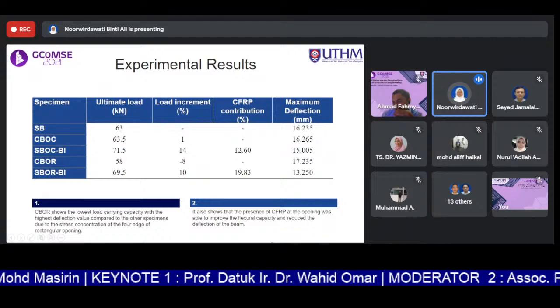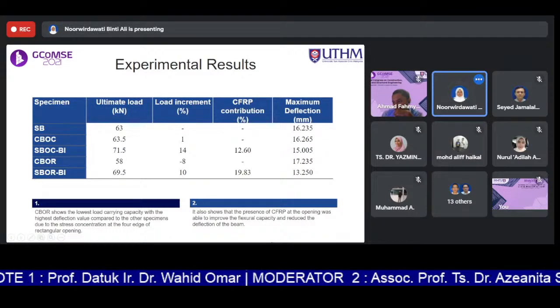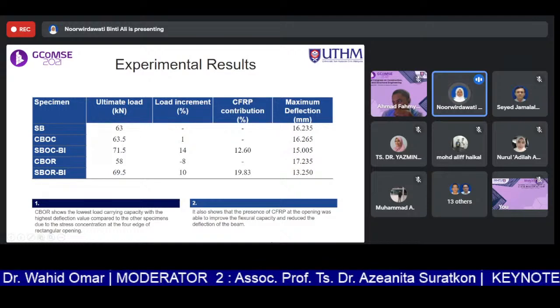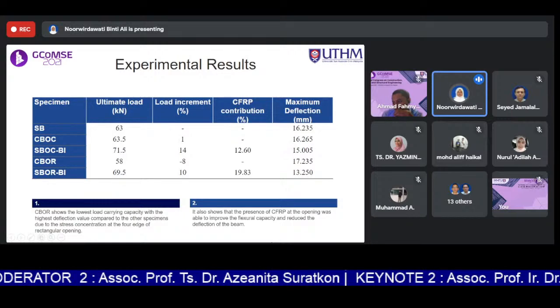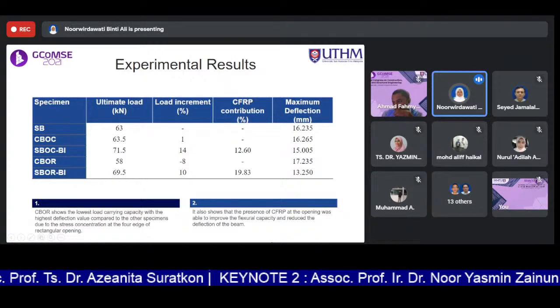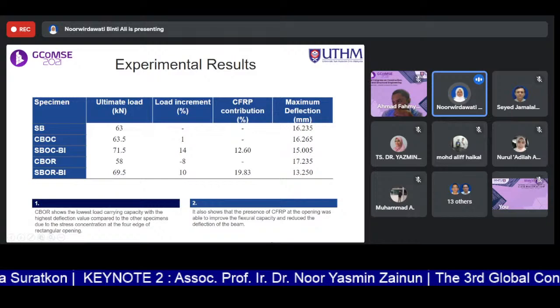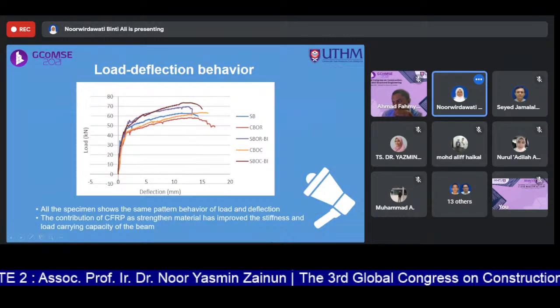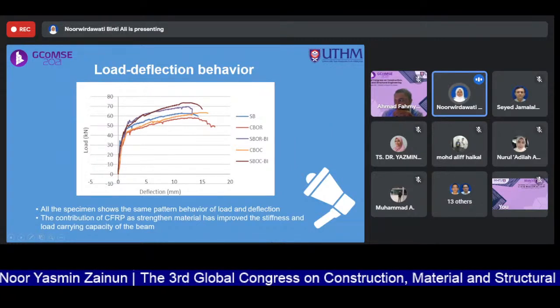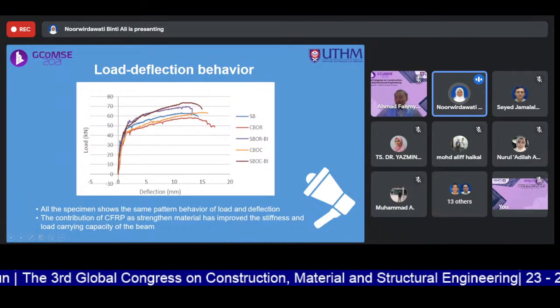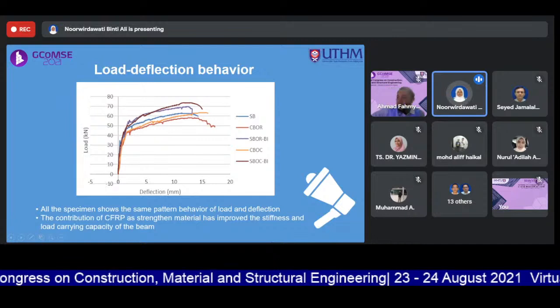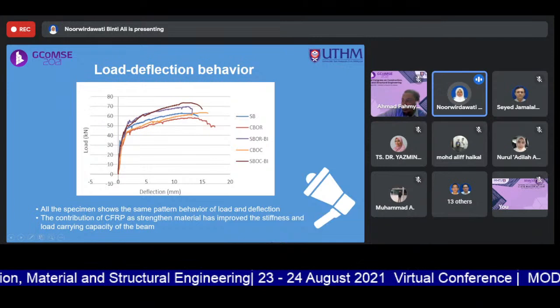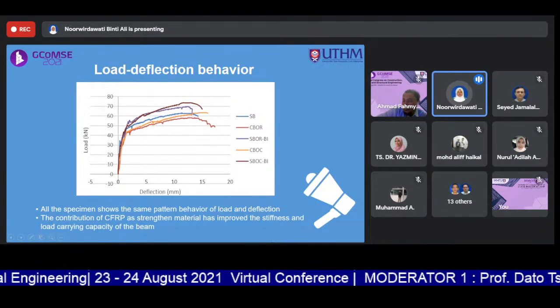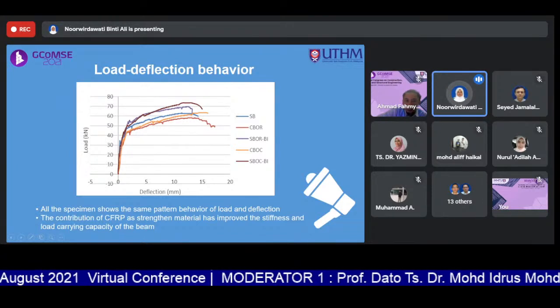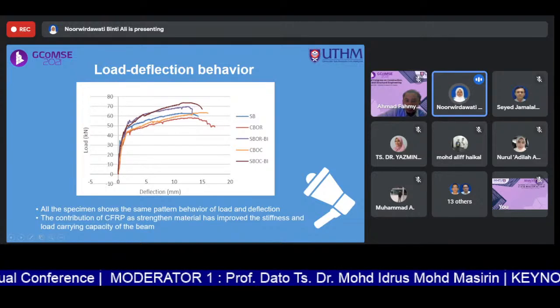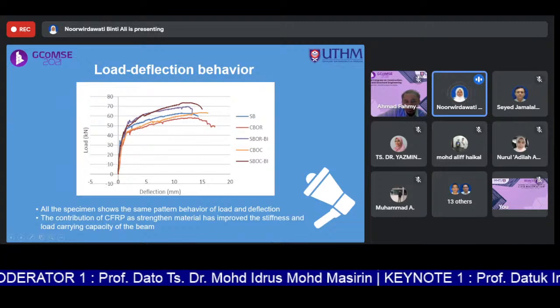This is due to the stress concentration at the four edges of the rectangular opening. And from these results, we can also see that the presence of CFRP at the opening was able to improve the flexural capacity and reduce the deflection of the beam. About the load deflection behavior, the trend for all specimens shows the same pattern. For the strengthened beam, the opening does not give much difference in the load deflection behavior. However, if we go into more detail, the CFRP has contributed to the increment of the stiffness of the strengthened beams.